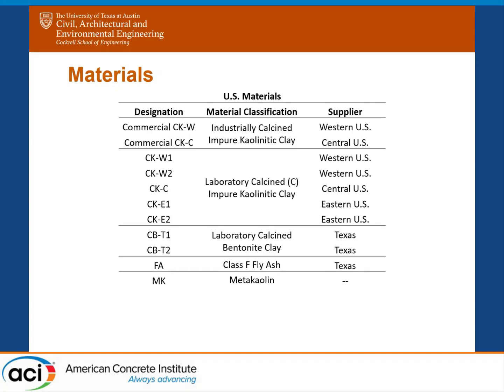The materials procured are a combination of two commercially calcined, or industrial calcined, impure kaolinic clays. So these were sent to us from the supplier already calcined. And then we also obtained raw clays from a wide geographic region, of both kaolinic clays and bentonite or montmorillonite clays. So a little bit on the naming of these, since we have so many materials that are very similar in composition, or at least the reactive components.